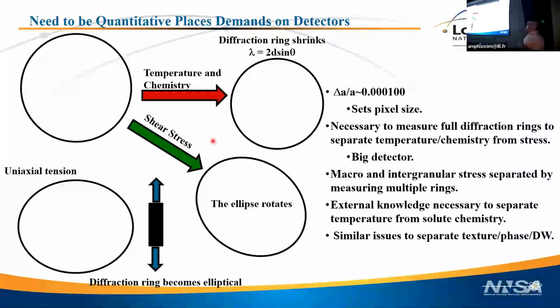All these issues come when you're talking about trying to separate texture, phase, and the Debye-Waller factor as well. Very similar set of problems. Now, one thing I haven't touched on here, both stress and texture are very much three-dimensional problems. If you're trying to do a dynamic measurement with X-rays, or neutrons for that matter, of texture or stress, you only get one 2D measurement, right? You measure the whole cone, but that's only a two-dimensional measurement.